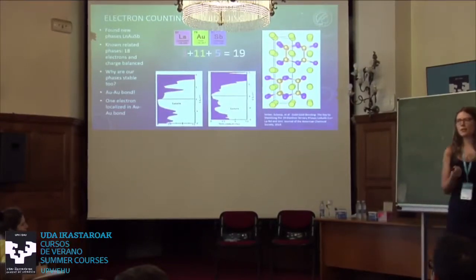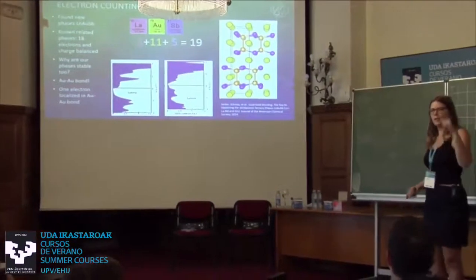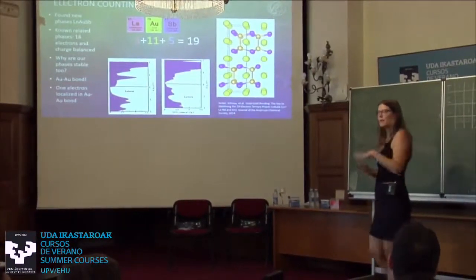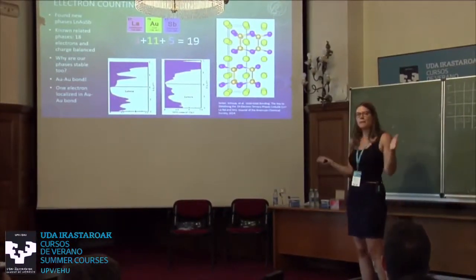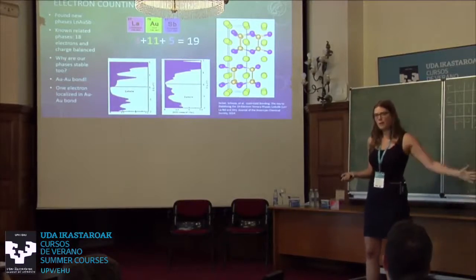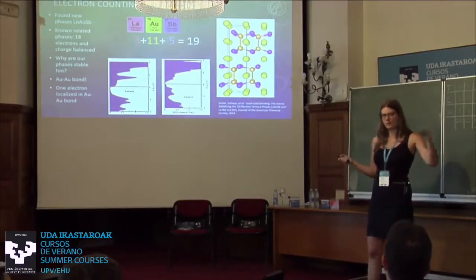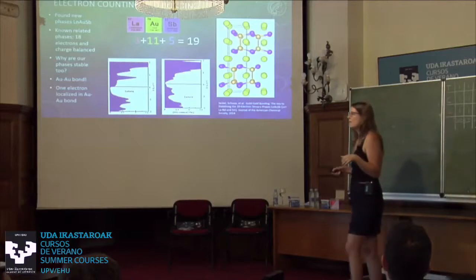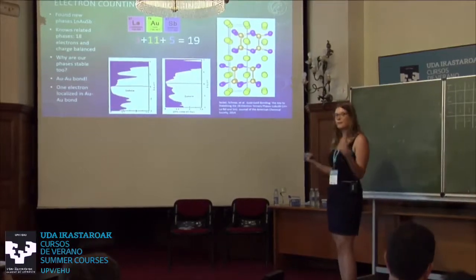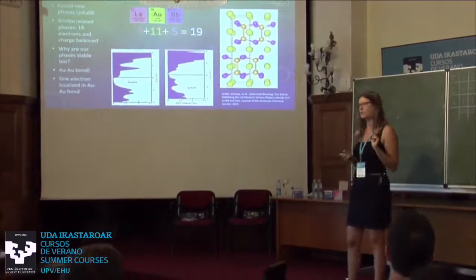So they're sharing electrons, they're forming a bond, and then those 2 electrons in the bonds are localized away from the valence electrons. They kind of move further away from the Fermi level, not to the core, but you could basically treat it like this. And therefore, you subtract 1 electron per phase, and you're back to a pseudo 18 electron count.